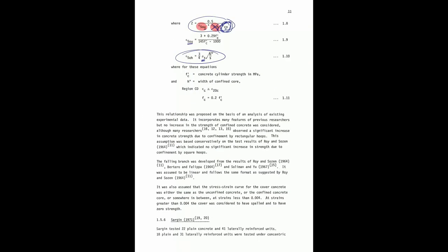In particular, in the moment curvature response, you will see. In practical situations, when you design, you limit the maximum strain to be somewhere around 0.003, according to the ACI definition of concrete failure, right? So you have just one state. When you compute the nominal moment, you just get one number.